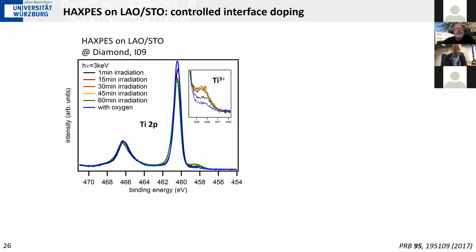So that means that we create oxygen vacancies here, and that is known. That's the Knotek-Feibelman mechanism. It was mentioned a few days ago by Ulrike Diebold. When you shine high energy light on an oxide, you very often create oxygen vacancies, and that's what's happening here. However, we can fill these oxygen vacancies again with oxygen.